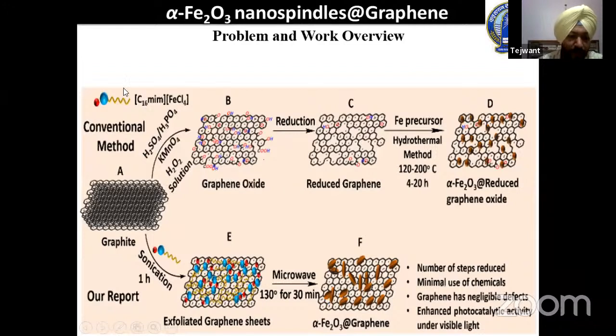On the other hand, what we have done is use an imidazolium based ionic liquid. I'll just highlight it: an imidazolium based ionic liquid appended with a 16 carbon long chain and FeCl4 as the counter anion. So this ionic liquid has acted as the template as well as the precursor for the preparation of iron oxide nanoparticles. In the first step, we exfoliated the graphene by bath sonication using this surface active ionic liquid. After exfoliation, the graphene sheets were decorated with the ionic liquid. When the aqueous solution of graphene having this ionic liquid was put under microwave irradiation at 130 degrees Celsius, we found the formation of spindle shaped alpha-Fe2O3 nanoparticles at the surface of graphene, as shown in diagram F. So I'll skip all these things.